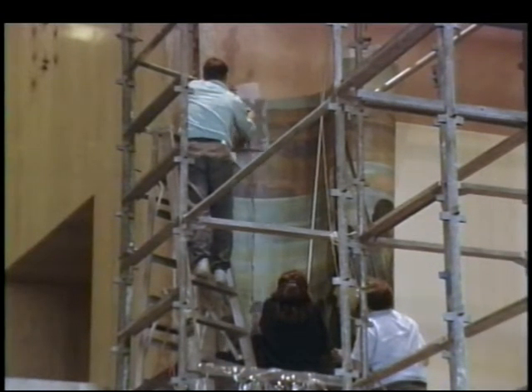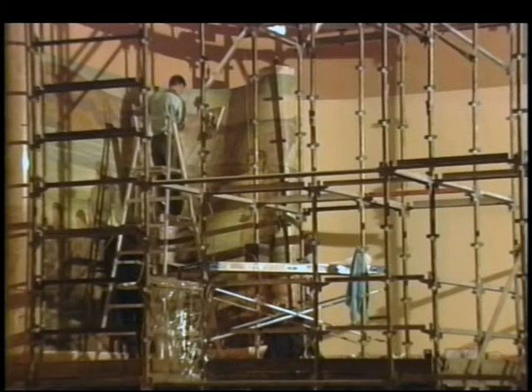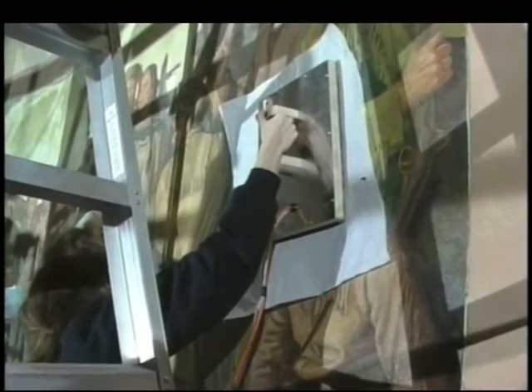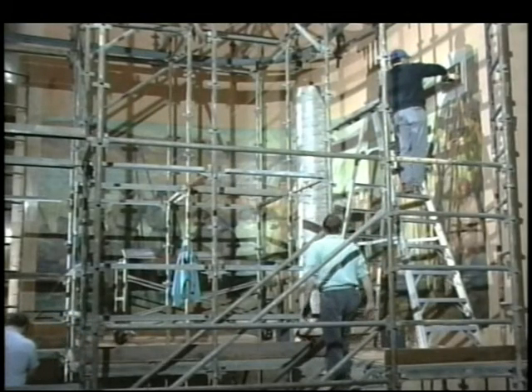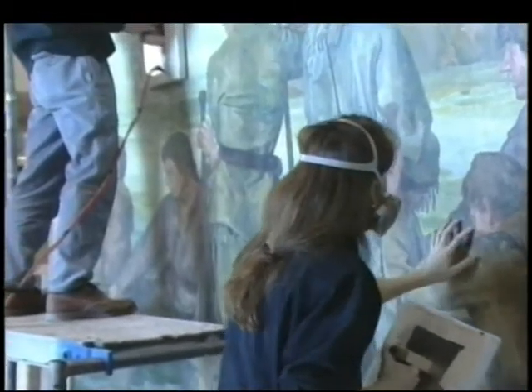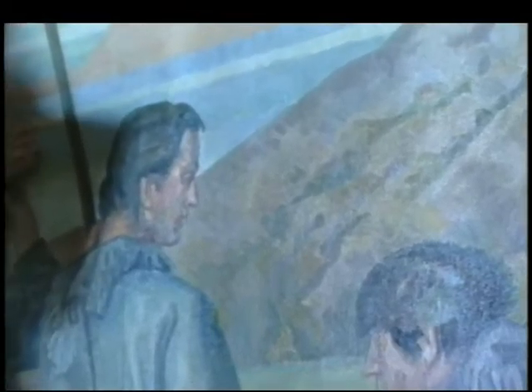The adhesive is an ethylene vinyl acetate, and it is activated at about 160 degrees. We have designed some special platens for raising the temperature and activating the adhesive using a thin 32nd-inch silicone pad that's embedded with copper wire and heats up based on resistance. The pads that we've designed not only heat a larger surface area, but they are safer to use. There's very little chance that the surface could be overheated, and obviously, we want to avoid that. Plus, the silicone is very soft and it conforms to the impasto of the paint.